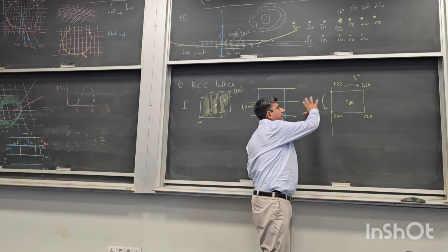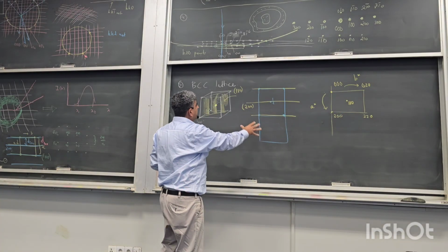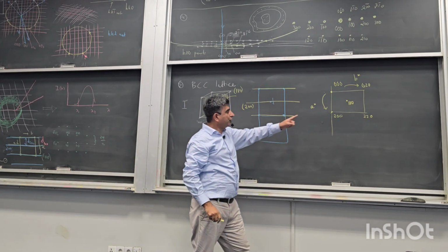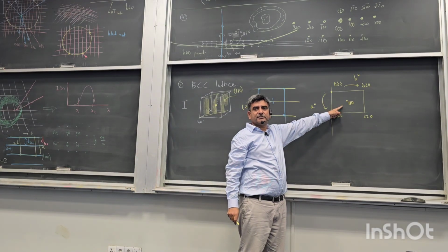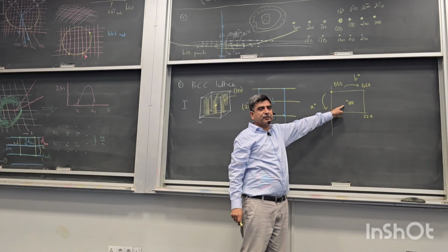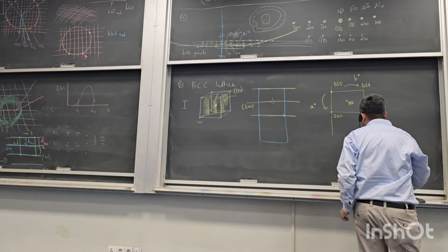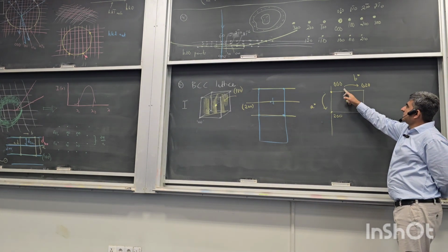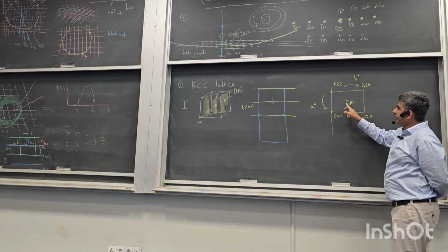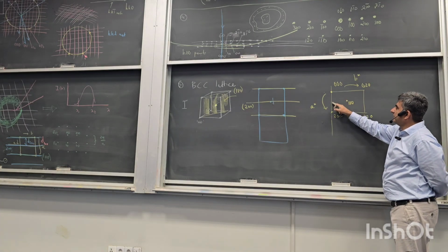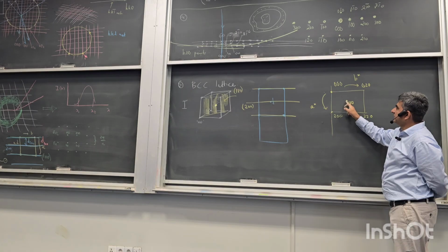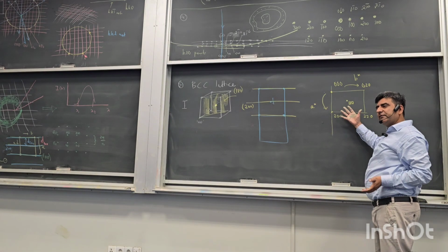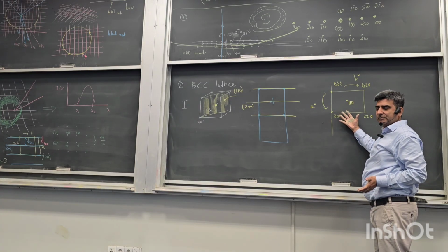So this is a view of the reciprocal space corresponding to the Fourier transform of the BCC lattice, and you observe that this is face centered. This has a point at the center of the face, and look at how we are counting the points. So from 0, 0, 0 you go to 2, 0, 0. So you jump in steps of 2 along the edges, and you jump 1 unit along each edge along the diagonal. You get another point. And then you repeat this in 3D, you'll get a face-centered lattice.